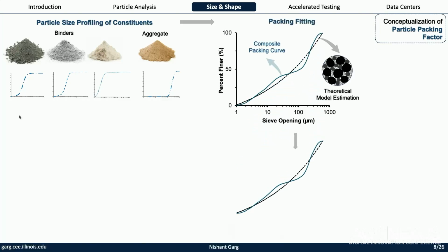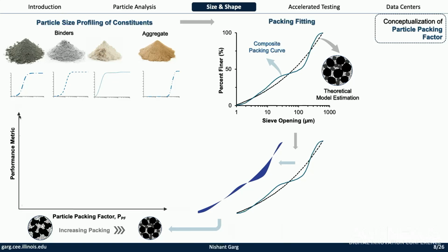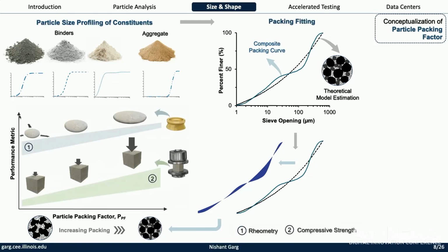Okay. Then measure the packing of our system and simply subtract between the ideal case and our case, and the difference, we quantify it, and we call that difference simply PPF, right? Particle packing factor. And it turns out this particle packing factor is very highly correlated to many properties ranging from strength to workability, right? So we see some selected results here of how this works.